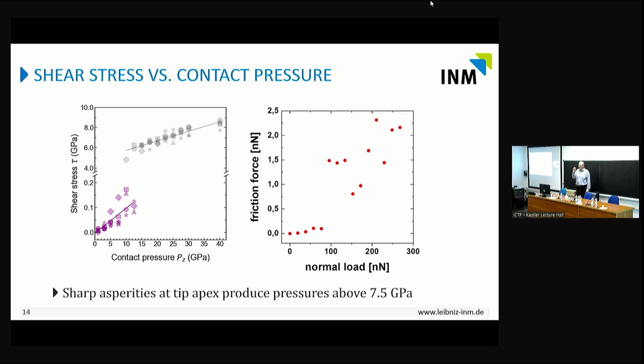And as I showed you already, we know that there's plastic flattening of the very sharp asperities at the tip apex. So it doesn't make sense to give too much detail on a Hertz model and the tip radius, because the tip radius that's essential for the transition is very small. I think we have small micro asperities that are being flattened. Overall, the tip radius is like 5 nanometers, but that would not give us this pressure at the relevant force.